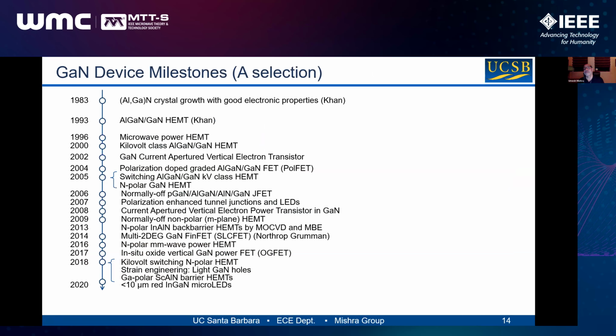Now, gallium nitride has developed over a very long time. In 1983, aluminum gallium nitride was first grown by Asif Khan, who's now at University of South Carolina, and who also demonstrated the first AlGaN-GaN HEMT in 1993. In 1996, my group basically made the first microwave power HEMT, and that basically kicked off a huge interest in gallium nitride for power. And then in 2000, we also made the kilovolt class AlGaN-GaN HEMT. So in 1996, we kicked off this microwave gallium nitride field, and in 2000, the power conversion field.